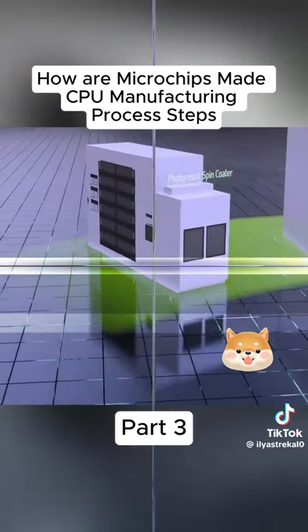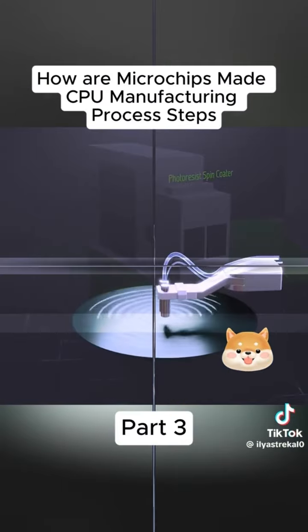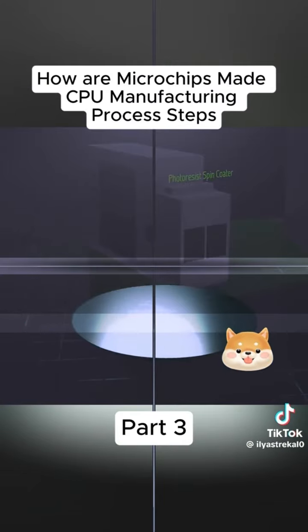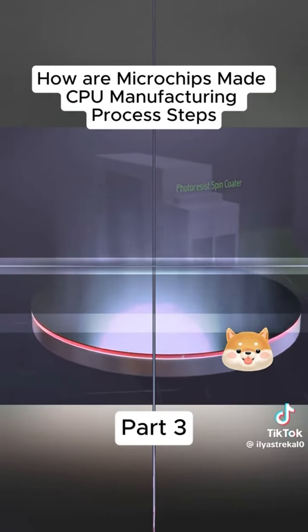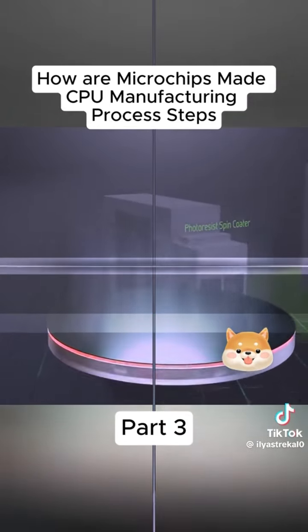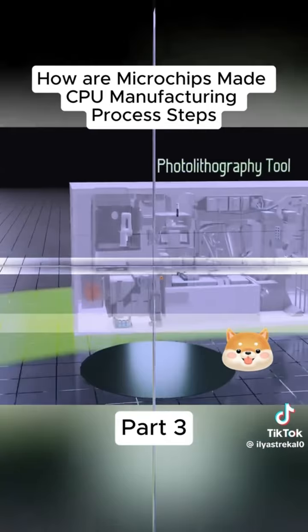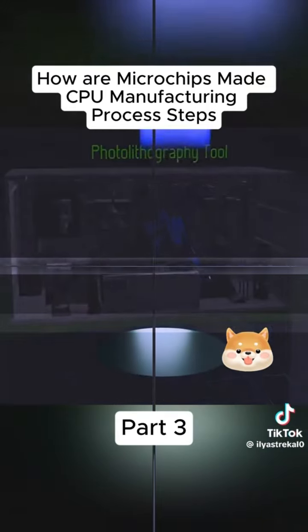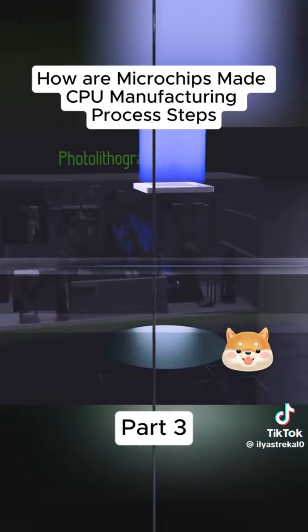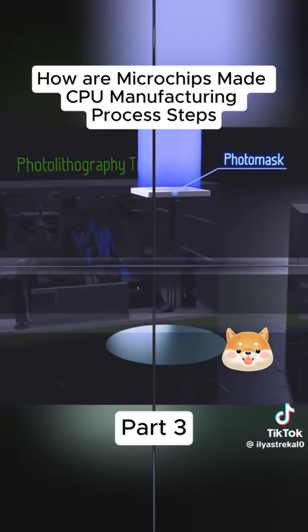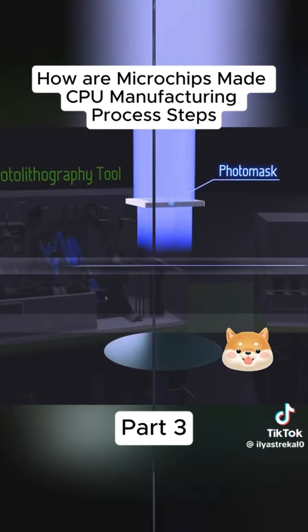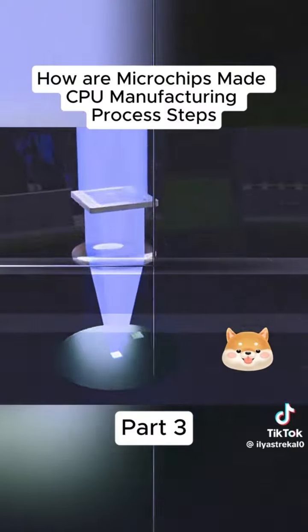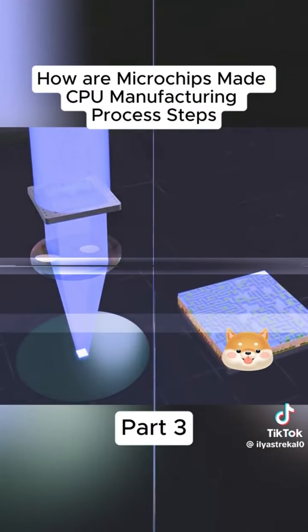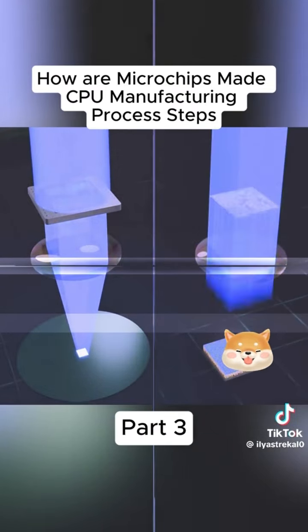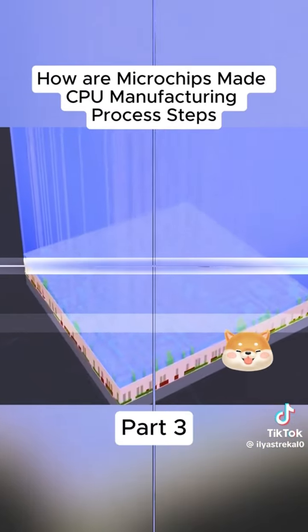First, the photoresist spin coater applies a light-sensitive layer to the surface of the wafer and sends it through a soft bake, where the wafer is heated in order to evaporate the solvent from the photoresist. Next, the wafer goes to the lithography tool, which shines UV light through a stencil, which is technically called a photomask. The light passes through the stencil and is then demagnified or shrunk down to produce a nanoscopic pattern on the wafer. Wherever the light from the stencil touches the wafer, the photoresist is weakened.